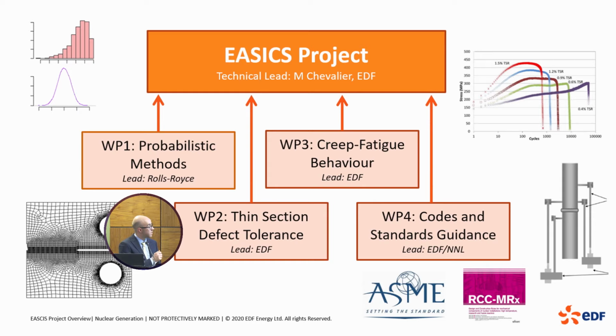And one of the key things around defect tolerance, and that's fracture and crack growth, nearly all the data that's generated is done using CT specimens like this, which are chunky, high constraint. And there's a lot of work out there, at low TRL level, that shows that that results in very conservative estimates of basically defect tolerance in thinner sections. So basically the defect tolerance of a thin section should be significantly better than we're currently assuming in the codes and standards. So this is all about developing that. So it's a significant test program looking at fracture and creep crack growth in thin section components to see if advice can be improved to improve the margins in that area.